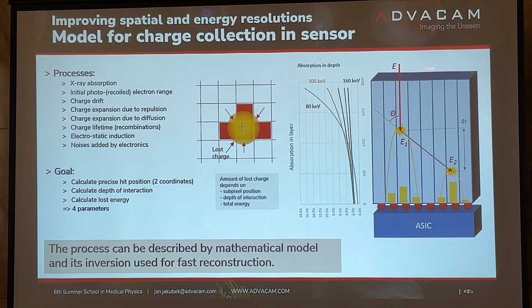Because if we have a detector like this one, which is of certain thickness, if the detection occurs close to the surface, then the charge has to be transported down. You can have some charge losses during the transport. For cadmium telluride, it happens. With silicon, we don't see that. So we can improve all those parameters we normally have. Position would be improved, depth would be determined, and energy would be improved.